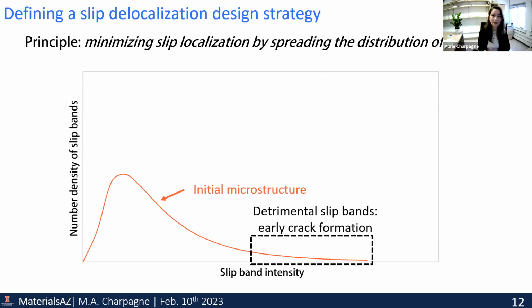All right, so the principle of this new approach is to minimize slip localization. And as I've mentioned, we have many slip bands that developed in the microstructure. Some of them are harmless and others are really bad for crack initiation. So if this is the distribution of the intensity of our slip bands and their number density, well, in commercially available materials we usually have some sort of distribution that looks like this. And the detrimental slip bands are the most intense ones. So these ones lead to early fatigue crack formation, and we want to get rid of them.